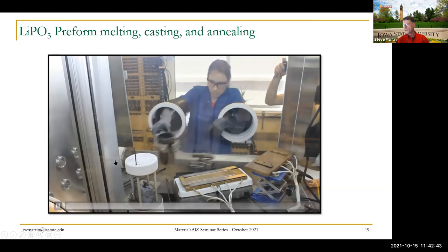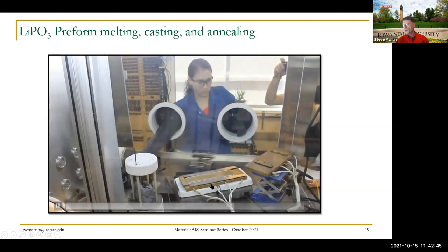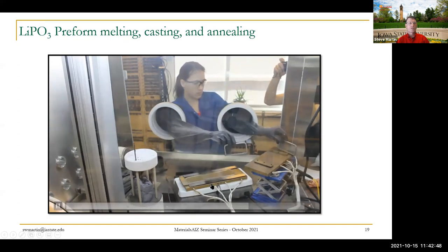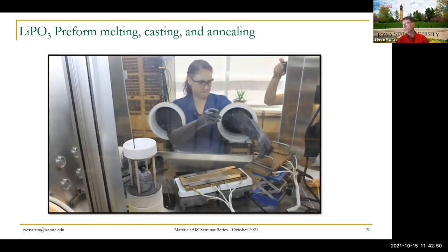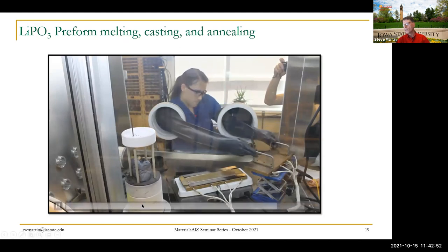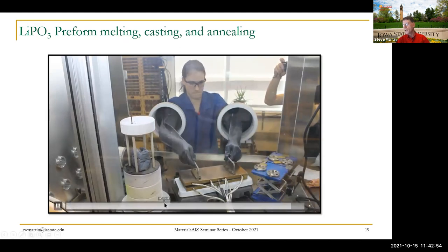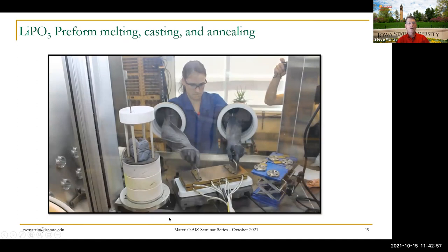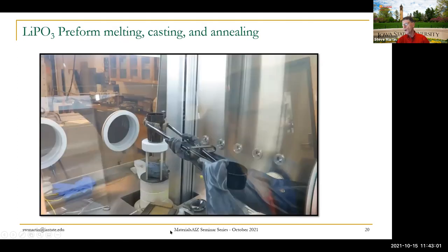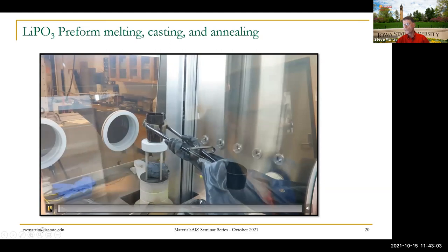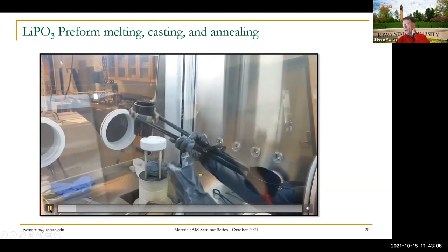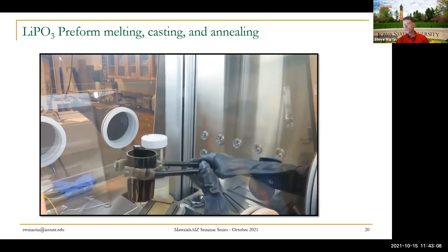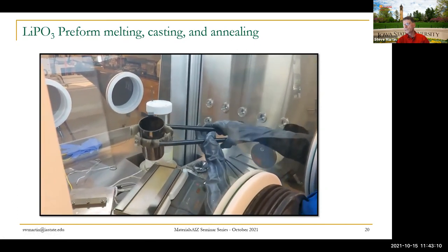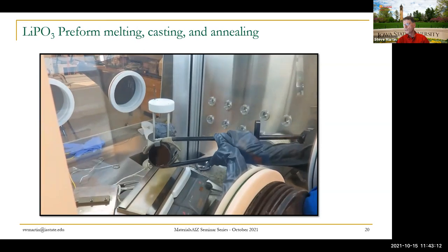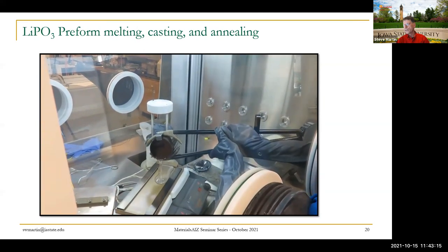And then the mold here is, you can see my pointer is sitting at about 290 degrees, just below the glass transition temperature, at the annealing point. She'll raise the furnace, this will go up into the furnace, and then she quenches that out. And that'll sit there and anneal for quite a while. Looking over her shoulder, just to show you in a little bit more detail, this is a vitreous carbon crucible inside the glove box, and she's swirling around to get it nice and uniform. And then she just pours that out into that mold.